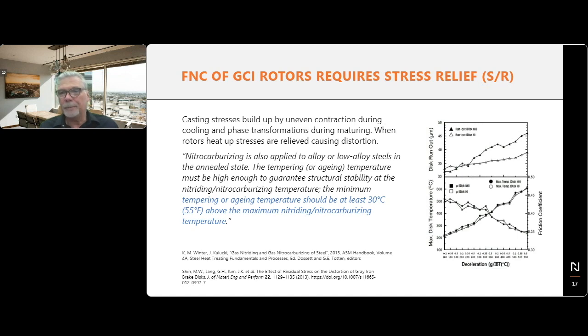So if you would machine and then subject the rotor or the disc to very high temperature in nitrocarburizing, which is usually around 1070 degrees Fahrenheit, or about 570 degrees Celsius. It could be slightly different, but it's usually between, let's say, 560 and 580, rarely up to 600. Then all those stresses would come out, and you would have a disc that loses its geometry or undulates. This is why typically before Ferritic-Nitrocarburizing or before even machining, the discs are subject to stress relief operations. Those stress relief operations are obviously done at a temperature that is higher than the process itself in order to prevent any warping.